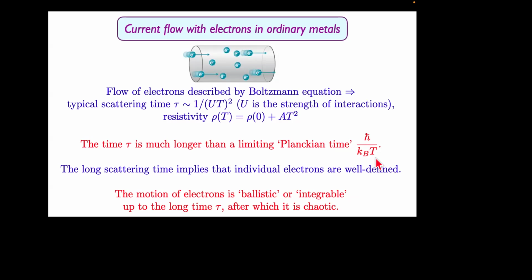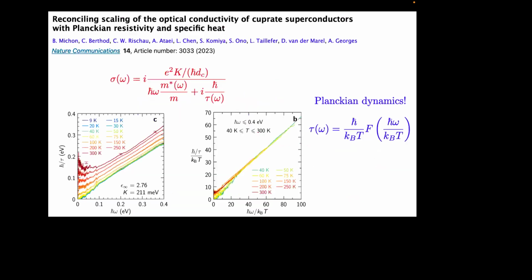Okay. And that really was the case in essentially all the materials that were studied until, very prominently in the cuprates, it became clear that this simply wasn't true. So what's going on? Well, that's the second problem we have to address. So here's some data of the optical conductivity. This is measured by shining light at a frequency omega and measuring the reflectivity and the transmittivity or things like that. And from that, you can read off various parameters of the underlying metal.